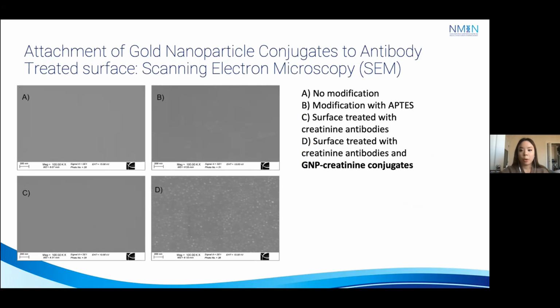We also performed a variety of microscopic techniques on the surface of our modified electrode to ensure surface homogeneity, as well as validating that the conjugates were actually bound to the surface of our electrode. So we used scanning electron microscopy, or SEM, which gave us some information about the microstructure of our surface and homogeneity and morphology of the surface.